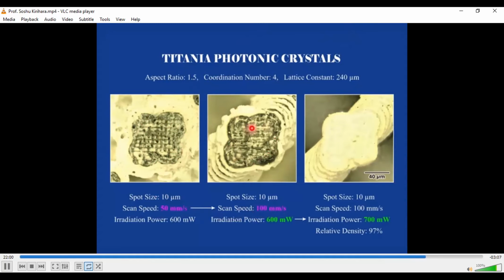However, you can see the black area remained. Of course, this is the remaining carbon elements, so the irradiation power was increased from 600 milliwatt to 700 milliwatt, so we can obtain a white colored micrometer order titanium dioxide lattice. In this case, the relative density is 97%. Okay, high density, however, not so high.